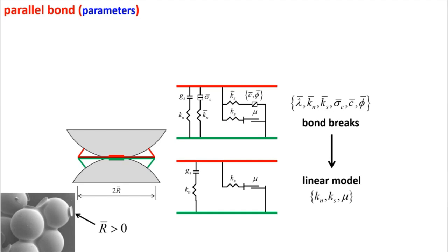And what people found is that for this parallel bonded material, no matter what they did, they could never get a ratio of UCS to tensile strength that was bigger than about 5. And I can show you dozens of journal papers of people trying things and failing, including Peter Cundall and me. We had all kinds of hypotheses. Oh, I think it's this. What if we just do this? Didn't work. What if we do this? Didn't work.